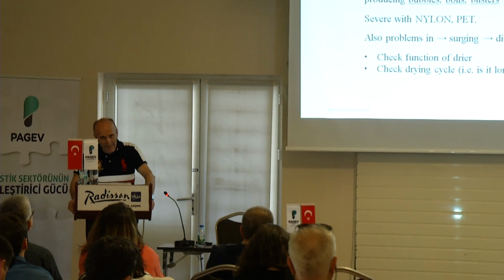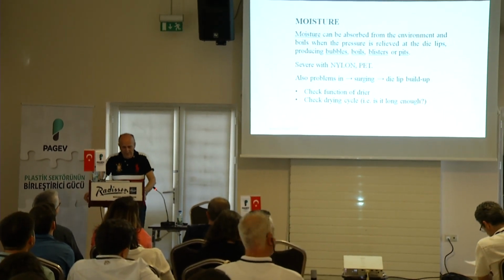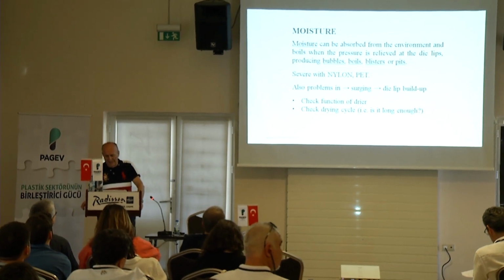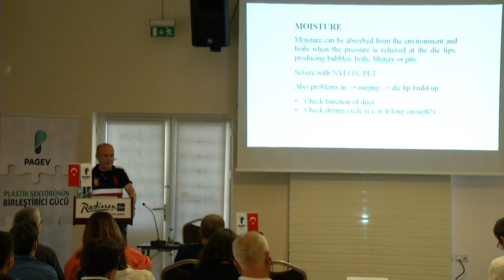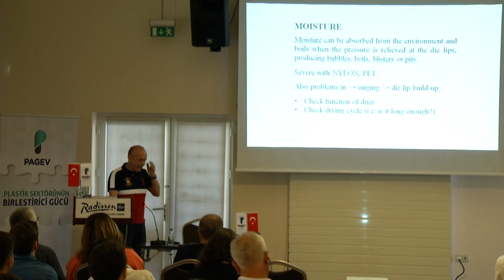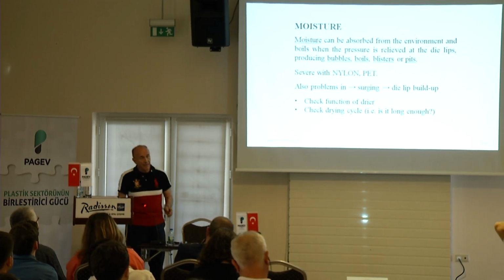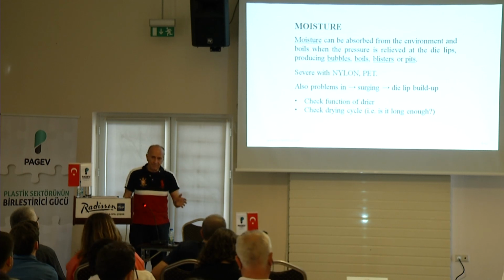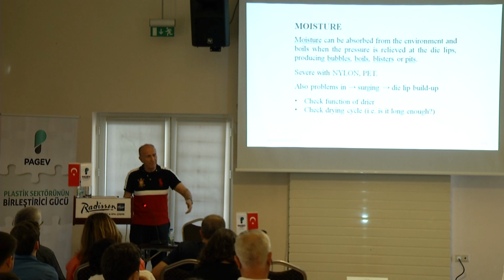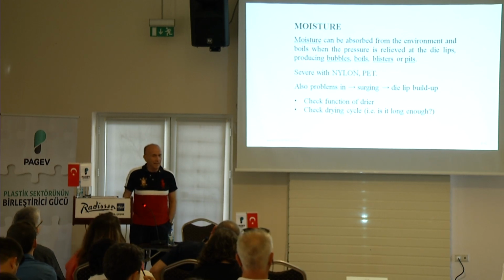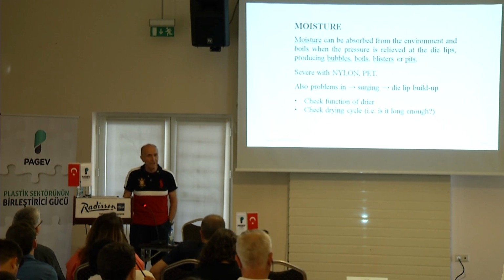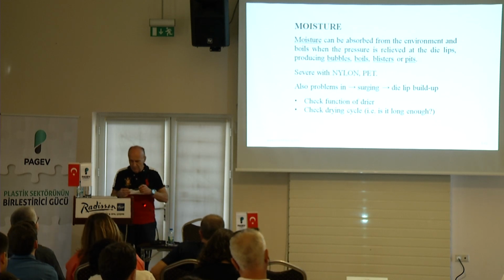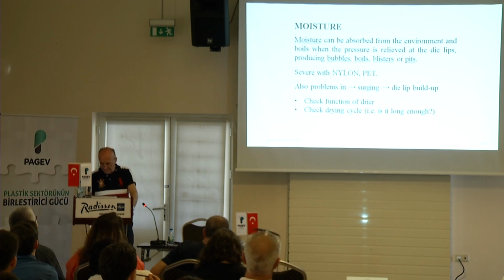Moisture, I did mention. Whenever you have temperature sensitive materials, be careful because of the problems that I mentioned, and you really should check the function of the dryer, but also ask the supplier of the resin. The supplier of the resin may have some good advice for you, like how long you would have to dry the material, or ask for advice from the supplier of the drying machine. You know, what do they say? Useful information that you may gather. Moisture is a big problem, and it can create a lot of other problems.